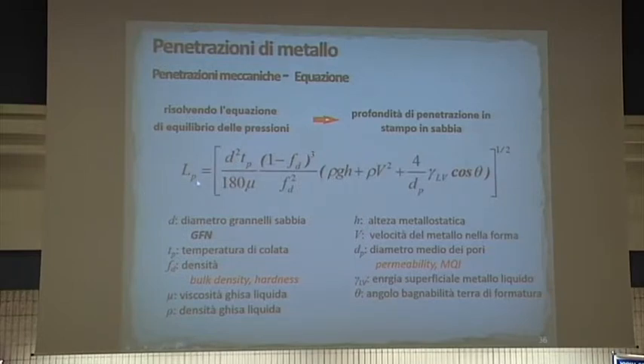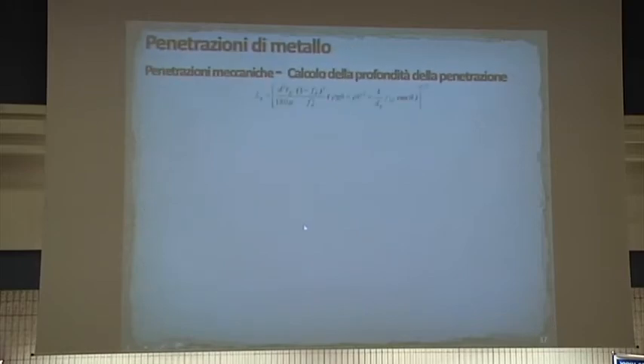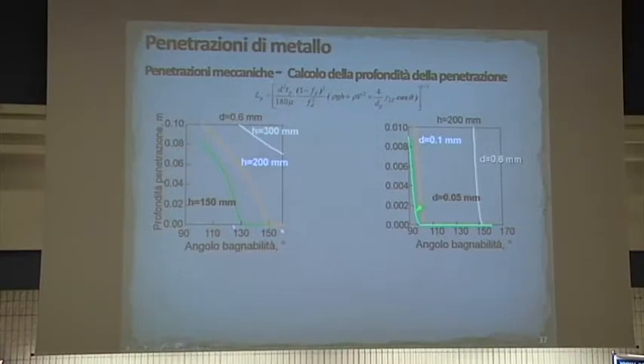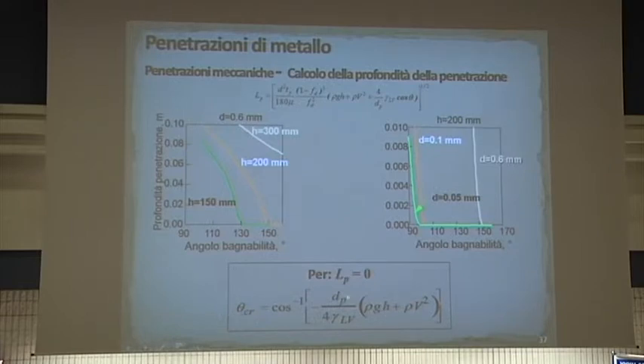And of course you are not interested in knowing how much the metal penetrates, you want it not to penetrate. So you take this equation and if you plot it, for example, against this contact angle, you find out that above a certain angle there is zero penetration. And so there is a critical angle. And so all we need to find is what's this critical angle? What does it need to be so I can always be above and have no penetration? And this critical angle depends, in this case, on the height, in this case on the diameter of the grain, so it depends on all of these variables. So we define this critical angle, and now we have to introduce all our foundry variables here.